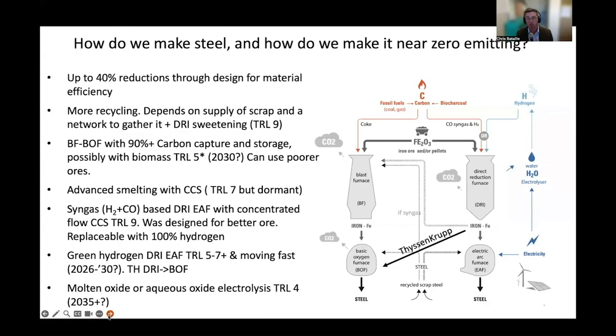We want to use material efficiency, obviously use as little steel as possible. But after that, we start looking at decarbonizing the core primary iron making process, where we separate iron from oxygen in iron ore. Most of that today is done with coal in blast furnaces. We use coal to make coke and coke to make carbon monoxide. And it's the carbon monoxide that carries away the oxygen in iron ore, leaving elemental iron, which we melt and then process into steel.